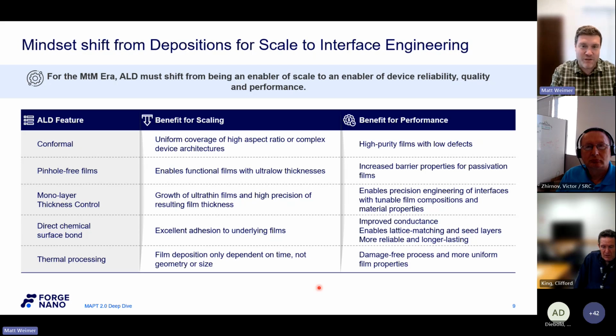So that's the first thing, to answer your second question first. Your first question about the uniformity of how ALD grows, again, that really depends on the incoming surface. This is really what we like to call the nucleation behavior of an ALD process. And again, that's highly dependent on the surface.